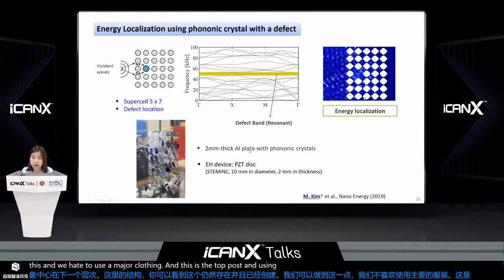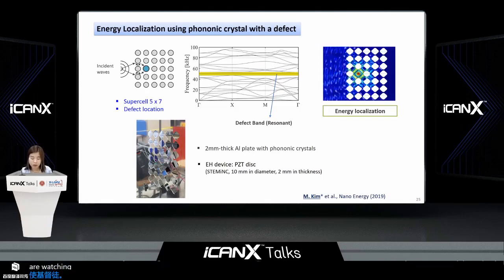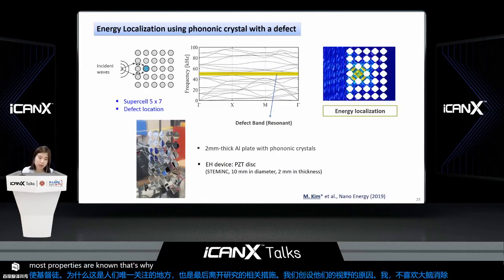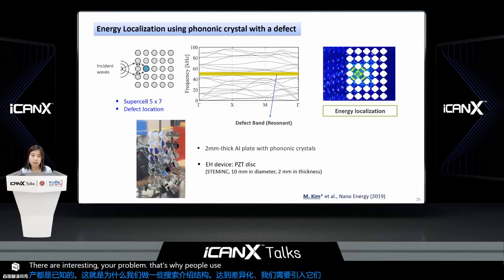And these are the octagonal holes, using a 2 millimeter thick aluminum plate to make the phononic crystals. The reason why we chose aluminum plate: a lot of people who are working on elastic wave related research normally use aluminum plate. There's a reason. We know the properties of the aluminum plate very well. So most of the properties are known. That's why when we introduce new structures, we can differentiate the newly introduced phenomenon from the existing material properties. That's why people use aluminum when we try to evaluate those metamaterial performances.